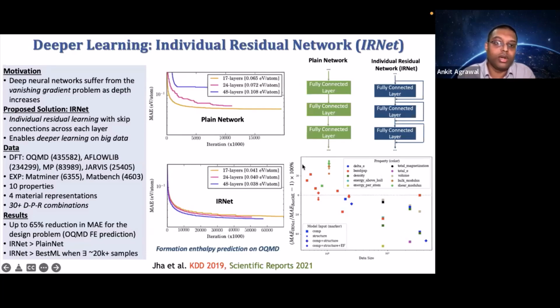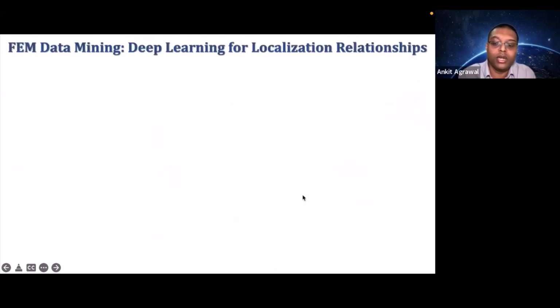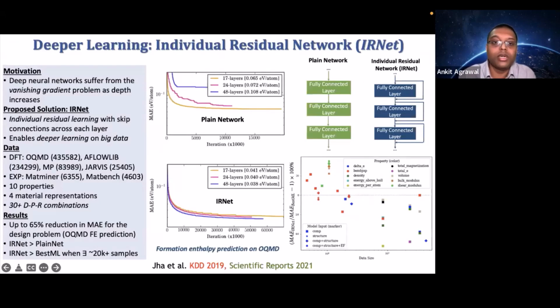So here you see on the y-axis the relative MAE, which is the MAE of IRNet divided by the MAE of the best machine learning model, which was identified by thorough grid search with over 10 machine learning algorithms. So basically, the best machine learning algorithm is on this x-axis. So anything below that is a lower MAE, so a better model. So we can easily see this trend here, that for very small data sets, machine learning is better than this IRNet model or deep learning.